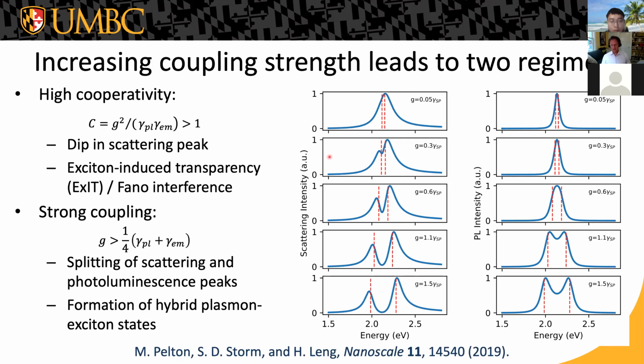No, I mean, they all involve the same line width. It's that they involve a different combination of the line widths, right? So the strong coupling is basically when the Rabi oscillation frequency is higher than the damping rates inside the system, right? And it's just a linear combination of those damping rates. The cooperativity depends on the ratio of, well, it's basically the ratio of the coupling strength to each one of the line widths multiplied together, right? So instead of having this linear combination, you basically have a product of the 2 of them. And so the emitter line width actually enters much more importantly in the cooperativity than it does in the strong coupling regime. So it's really just that difference that allows you to have, for example, this regime where you have relatively high cooperativity but not have strong coupling.